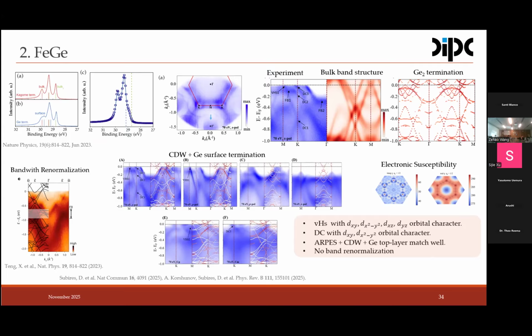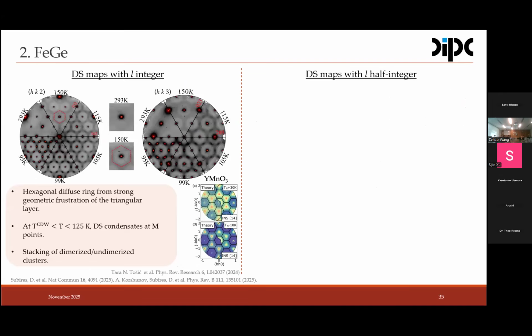We can actually take the charge density wave antiferromagnetic phase plus germanium surface termination, and we can match the flat band at gamma, which is a surface band, and the Dirac velocities crossing the Dirac band. In any case, I would agree with any of you if you think that with this huge number of bands, many bands can match any feature in the spectrum. But at least we get a better match between ARPES and DFT.